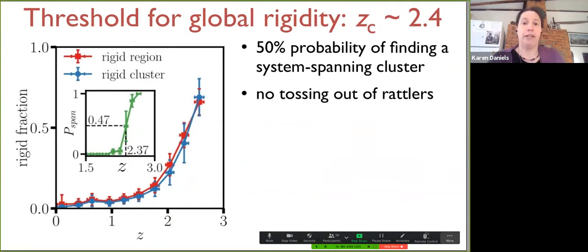We also can figure out what the threshold for global rigidity is, right? So if we define that as having a 50-50 probability of finding a system spanning cluster over all of our examples, and importantly, we do not toss out any rattlers here. Every particle that's in the system is in the system, okay? And I think this is really important because, again, like I said, it's not just a local calculation about that particle. When we're calculating the rigid clusters, any particle that's in contact can be contributing to stabilizing that cluster. And so in the next time step, it may be needed, right? So no rattlers are tossed out. This is truly the Z for the system, as best we can determine it from experiments.